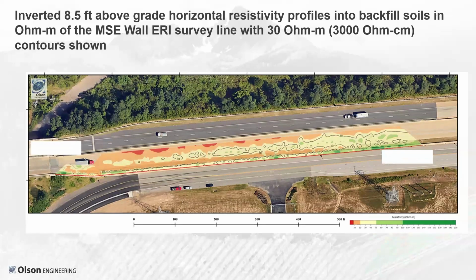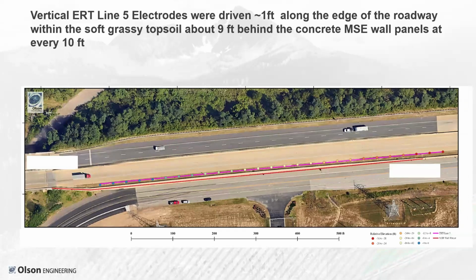Similarly, here's our 8.5 foot above grade survey that was inside of the wall, and we got pretty repeatable results between the two, not too different. And then lastly, we did another survey from the top down to get a little bit of information at the top because we weren't able to get electrodes way up at the top of the MSE wall. These are just points colored by GPS. So we have higher elevation on the left side towards the bridge, and then we get lower elevation on the right. And we had the same 84 electrode system used at the top.